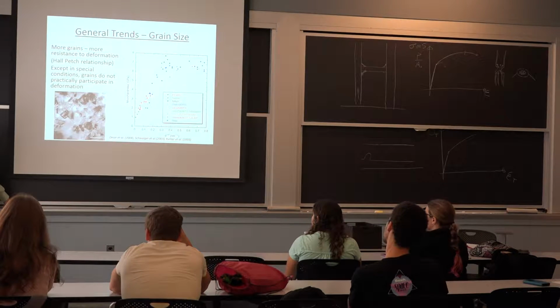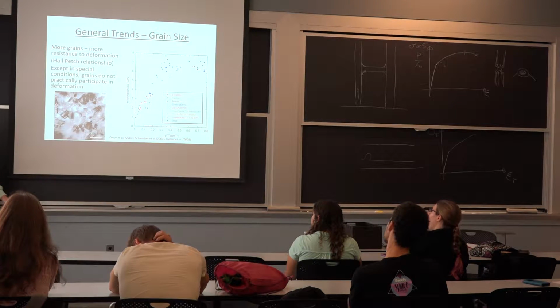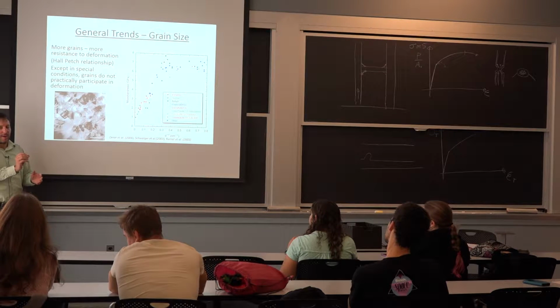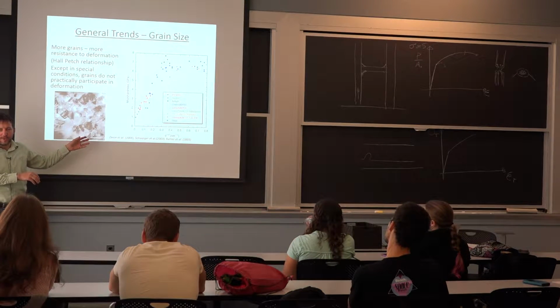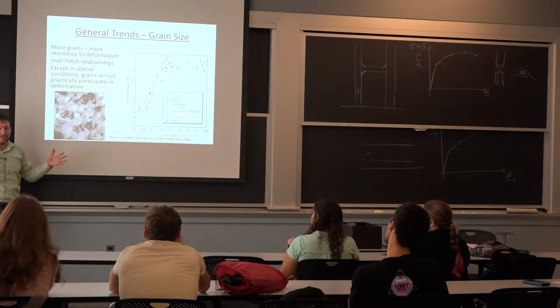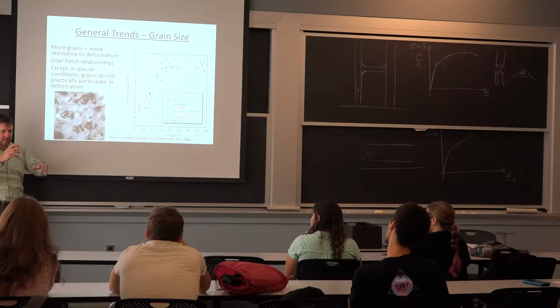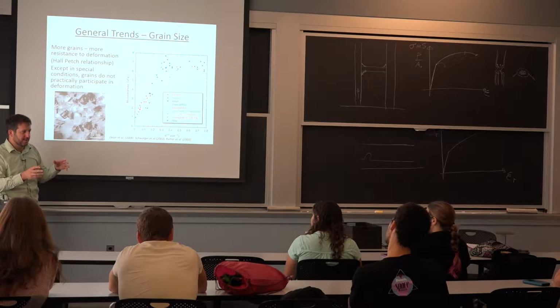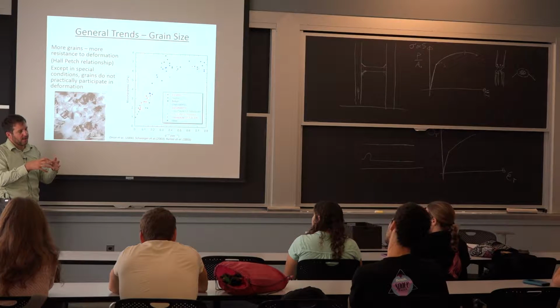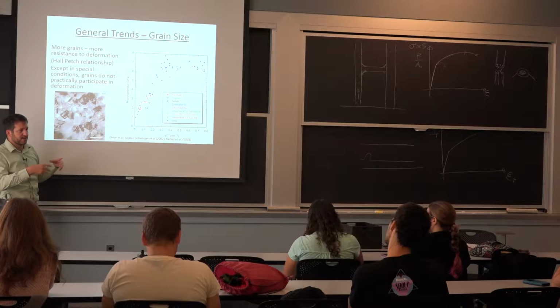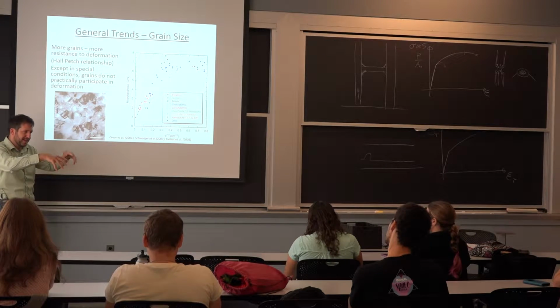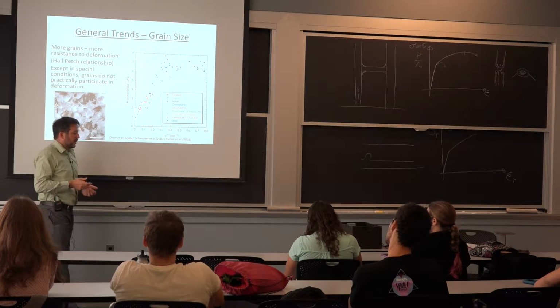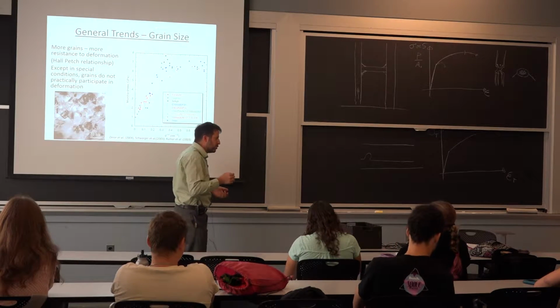The concept there, because I'm going all the way from very general here to specific, between a grain that's almost a millimeter, 100 micrometer, and then nanometer range, what you do is you force the entire system of dislocation interaction, like all these Frank-Read sources and everything going on in the material, you constrain it to a smaller area. Because these dislocations, they don't go across the grain boundary very well. It's a high energy zone, so they tend to stay within them. So perhaps for you, that's a kind of an intuitive way.